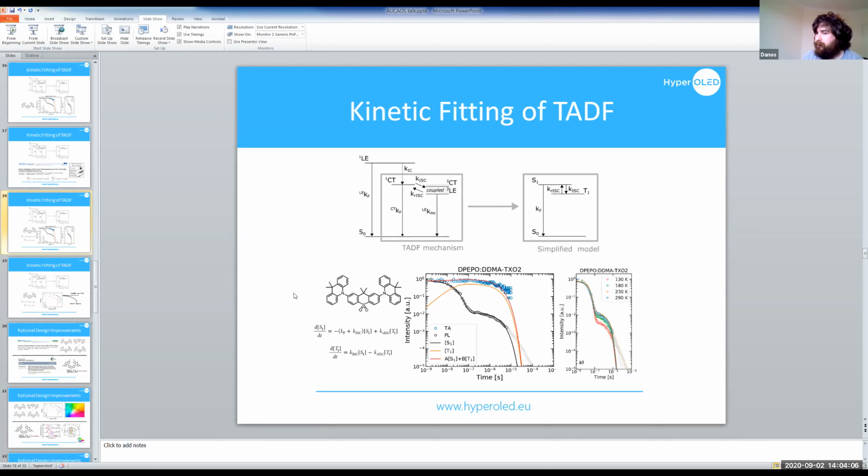From an applications point of view, you can get away without it. The historical development, though, was that people were saying, we've got a CT triplet from phosphorescence, we've got our CT singlet, they're very close together, and yet this particular TADF material is not working, whereas some other one where they appeared to be further away was working. So to rationalize how some materials appeared to have low singlet triplet gaps but were kind of crappy, whereas other ones had much bigger gaps but were working very well, the key piece of understanding was to recognize that sometimes you're not measuring the triplet state that's directly active.